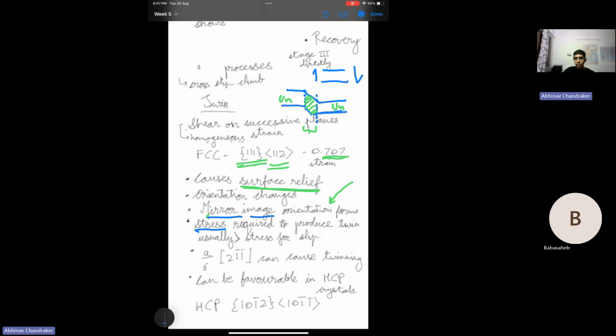So that's why at lower temperatures and higher strain rates, where the CRSS for slip becomes very high, that for twinning does not change so much, so twinning becomes more favorable compared to slip. One mechanism which is hypothesized is that the partials have a role to play in the formation of twin. By the movement of partials over successive planes, initially faults are formed and then twins can form as they stack on successive planes. In FCC, it is a/6 <1 1 bar 2 bar>. So this partial based mechanism is for FCC only.